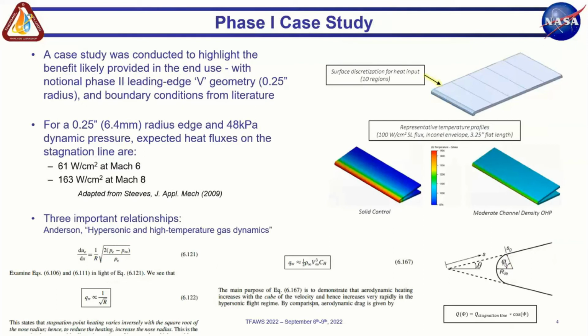At the beginning of the phase 1, we performed a case study to highlight the utility in actually using an OHP structure, and in doing so compared it to solid metal. The focus here is comparison to other metallic hot structures, not necessarily ceramic matrix composite development. In this case study, we did a little bit of self-teaching about aerothermal heating for hypersonic leading edges. The output is what sort of fluxes are generated at the stagnation line for modest radii, not super sharp, but quarter-inch type radius leading edges at Mach 6 to 8. You generate these sorts of flux levels at that stagnation line.